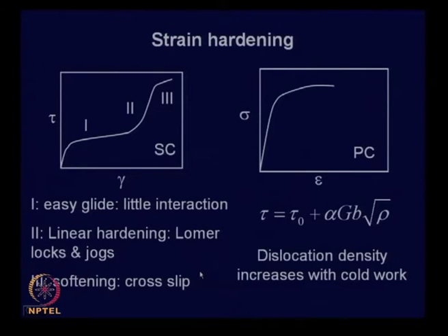Now, strain hardening we have seen, this is a typical deformation behavior of a single crystal. We talked about 3 stages: period of easy glide, where there is little dislocation interaction, whereas in stage 2 it is a period of linear hardening, where dislocation interaction takes place, Cottrell-Lomer locks are formed, the jogs are also formed on the dislocation, and this makes the movement of dislocation difficult. So, therefore, there is a high amount of strain hardening, and then when the stress increases significantly, here again another mode of deformation which is responsible and leads to a little bit of softening, that is cross slip.